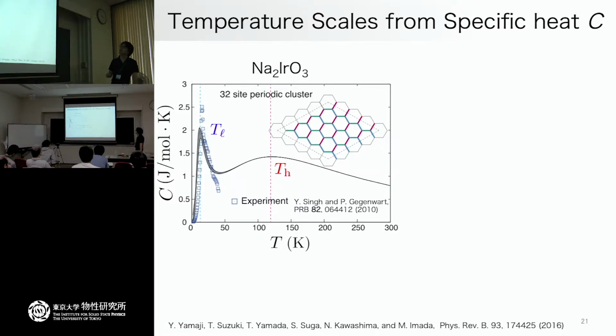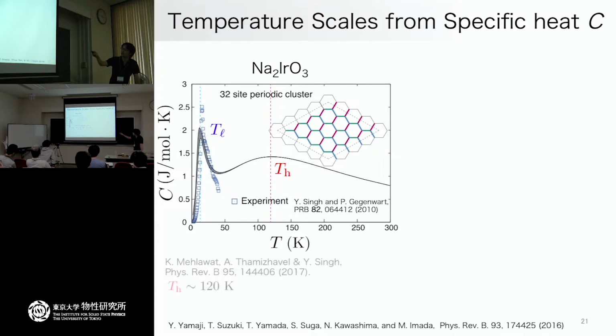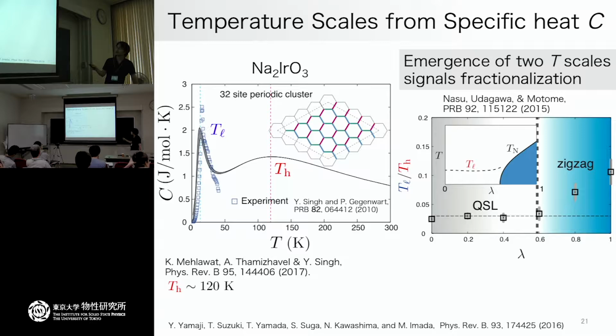And if you look at the heat capacity and compare with the experiment, the agreement is more or less good, because this is calculated for the ab initio Hamiltonian for the sodium iridate with 32-site spin clusters. We can directly compare with the experiment without any adjustable parameters. Here, this is the experimental result of the heat capacity. It shows a good agreement. And later, this motivated our theoretical prediction of the high temperature heat capacity. The Indian group re-examined the heat capacity, and they found a high temperature peak exactly around this temperature.